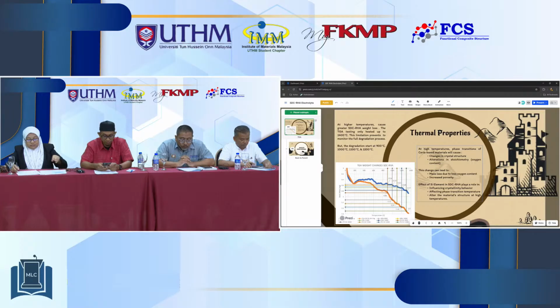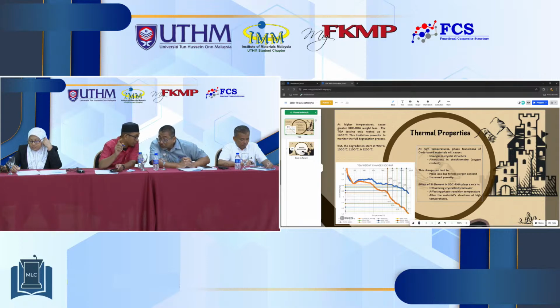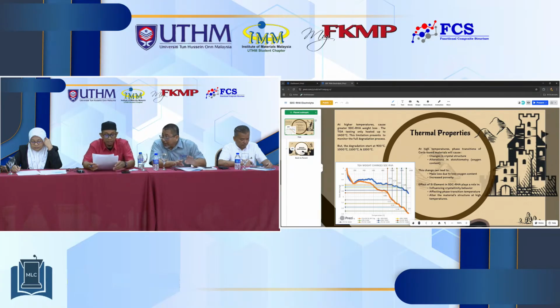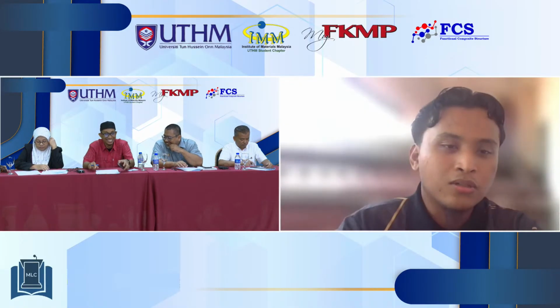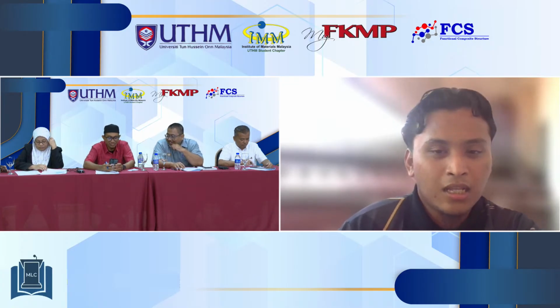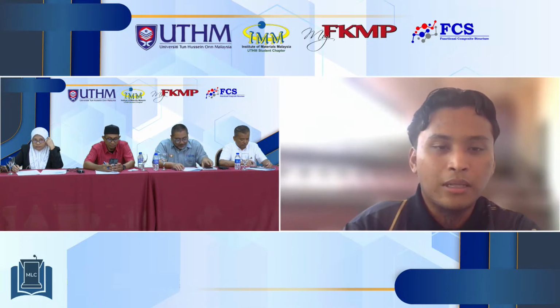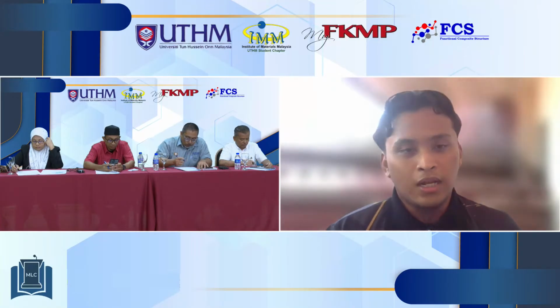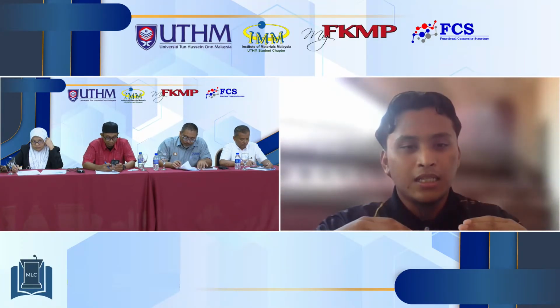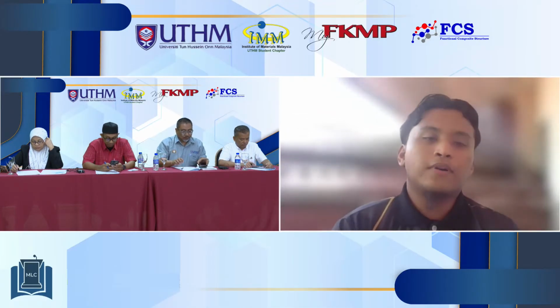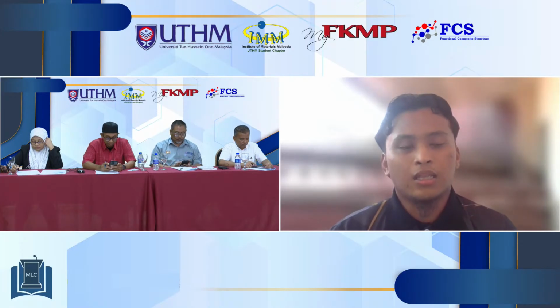Okay, as you can see from the degradation mass, when we burn at 900 Celsius to 1200 Celsius, there is a change in mass, 0.56 until 0.68. So this change makes the SDC itself less dense, so it has voids in between the structure. So the presence of silica element in the RHA is expected to fill up the voids in between the particles of SDC itself. So it will increase the density of SDC itself to achieve electrolyte properties in terms of density.